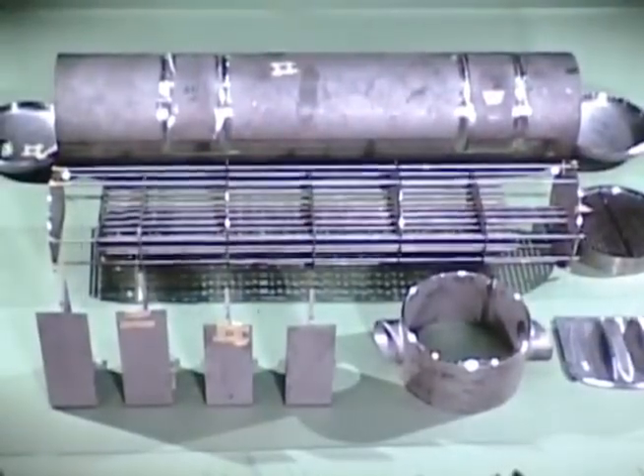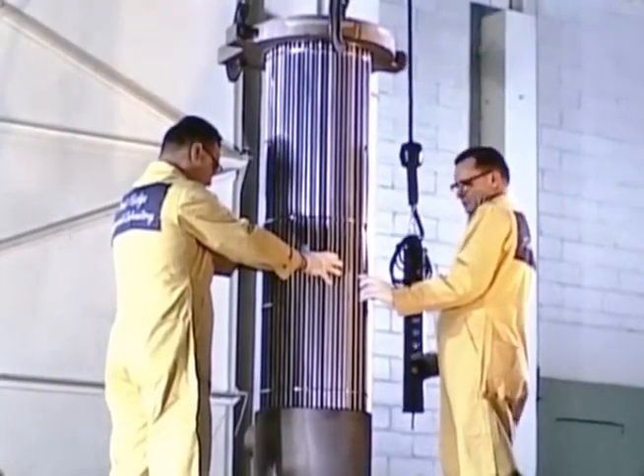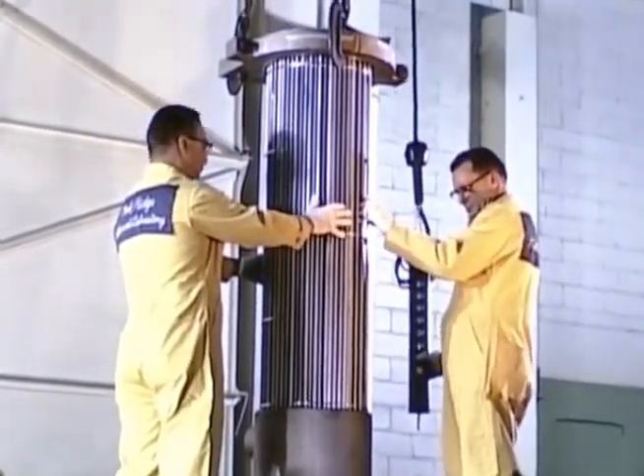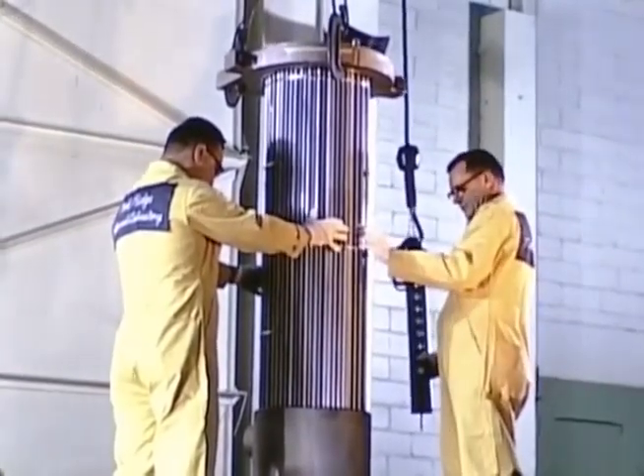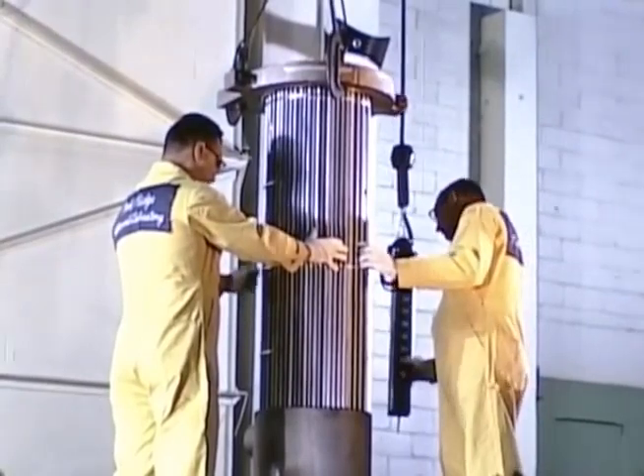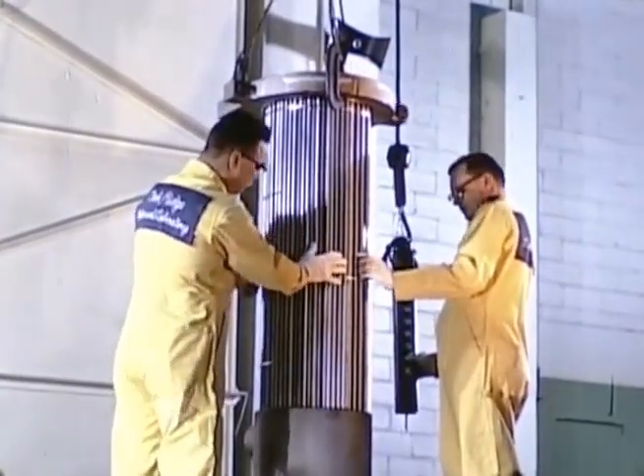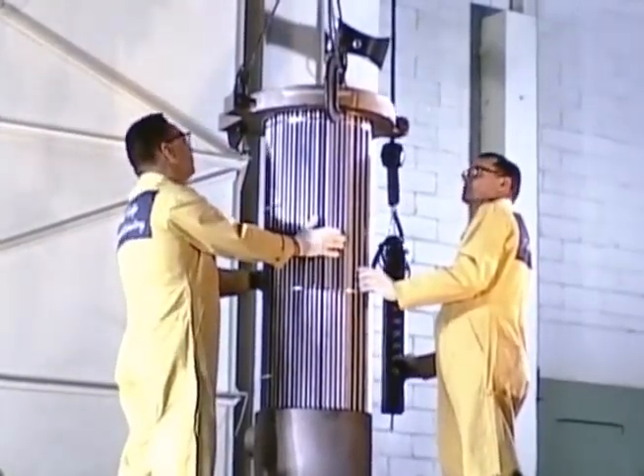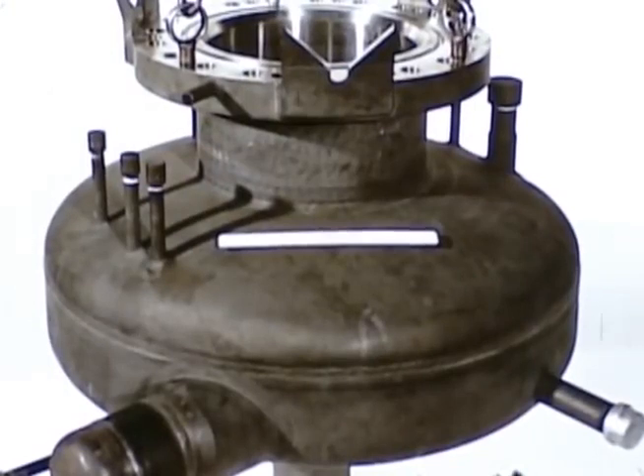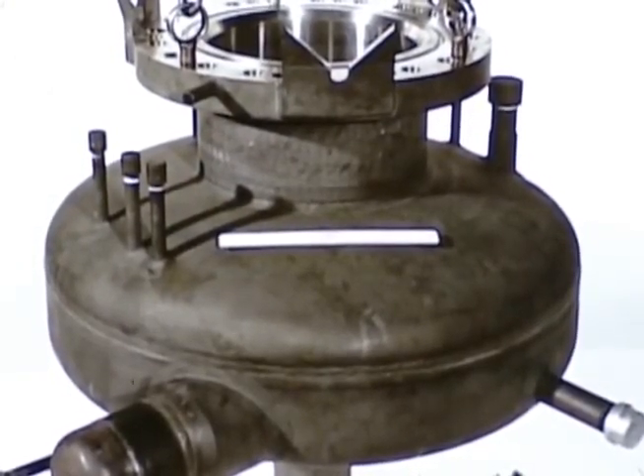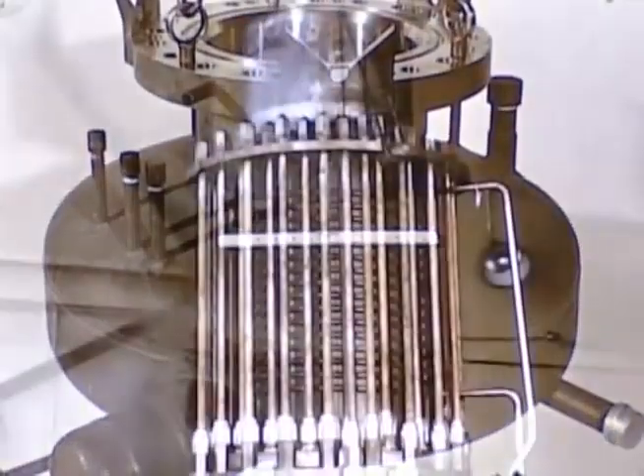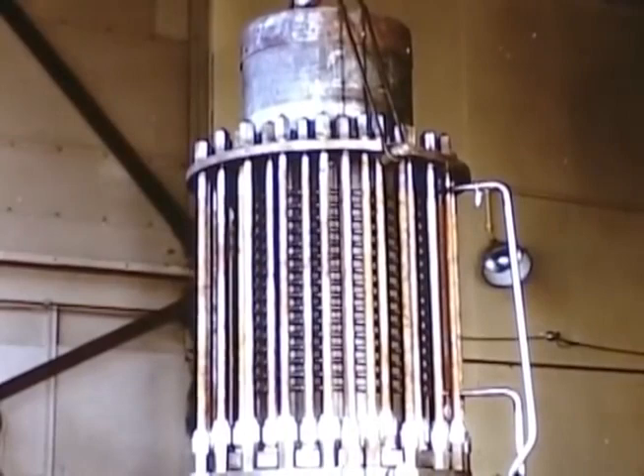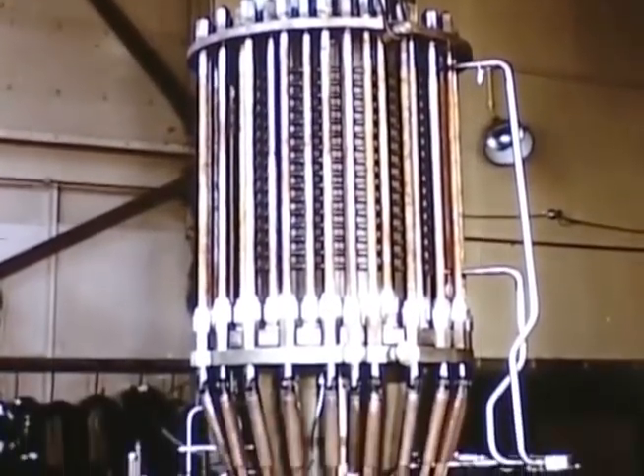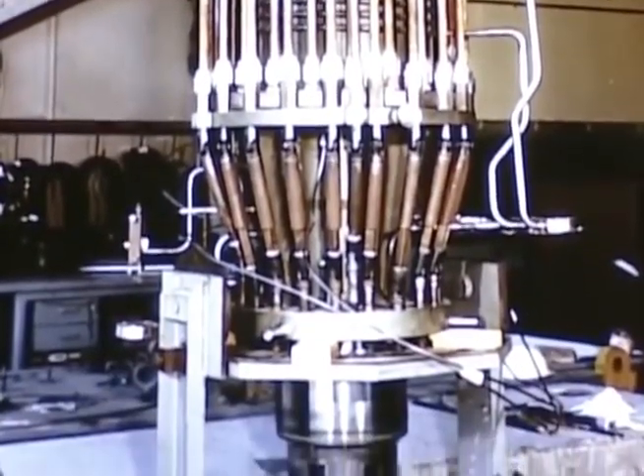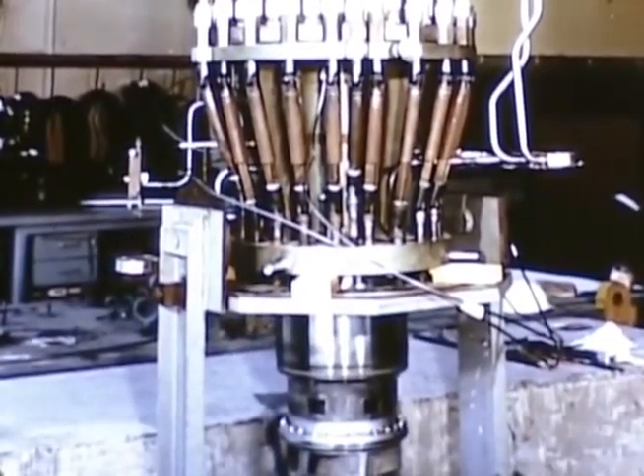The horizontal shell and tube primary heat exchanger is about 8 feet long. Its U-shaped tubes, a half inch in diameter, were fusion welded and furnace back brazed in a hydrogen atmosphere to the tube sheet. The bundle contains spacer bars tightly laced in two directions through spaces between the triangular pitched tubes to eliminate flutter and vibration. The fuel salt pump bowl serves as the pump sump and normal volume to allow for expansion of the salt. This fuel pump rotary element with water-cooled drive motor, bearing assembly, bolt extensions for remote replacement, and impeller circulated molten salt at 1200 degrees during the non-nuclear run-in test.